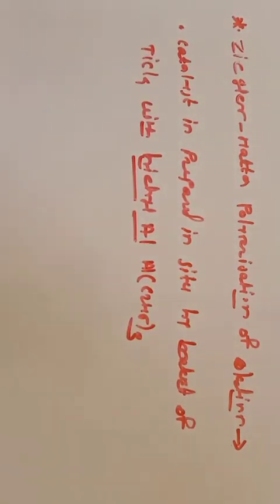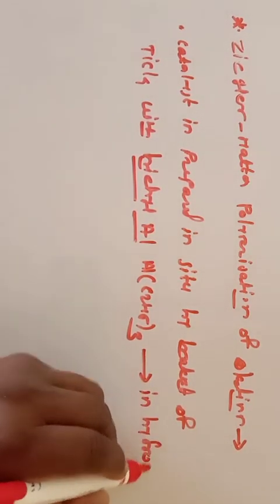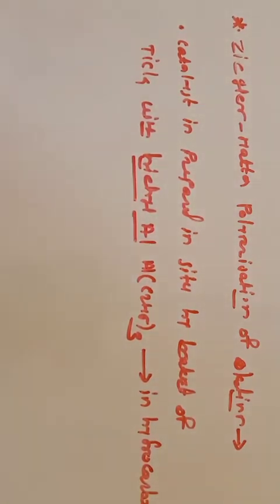The catalyst is prepared by the reaction of titanium tetrachloride with triethyl aluminum in a hydrocarbon solvent such as n-heptane. TiCl4 and triethyl aluminum react together to give a polymeric, insoluble and fibrous form of TiCl3.